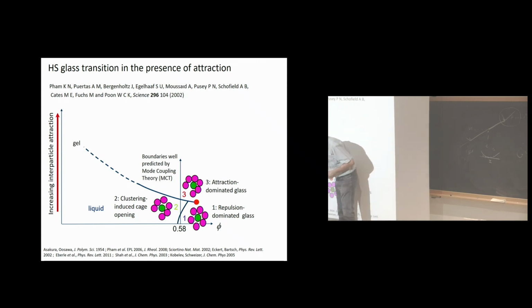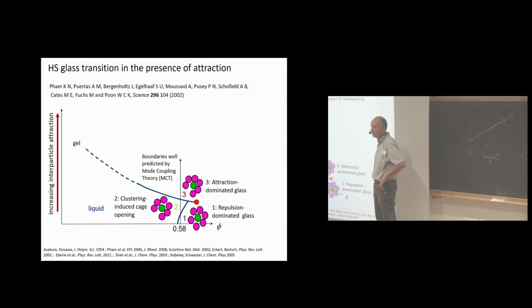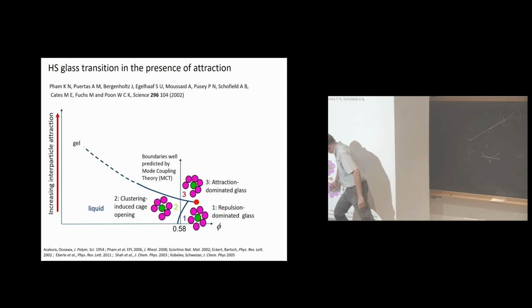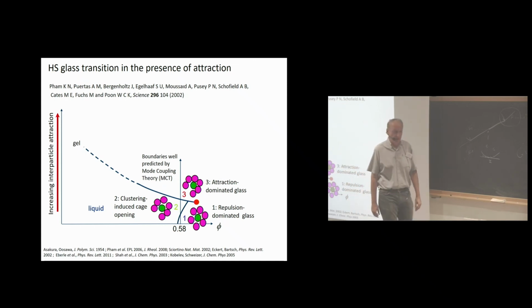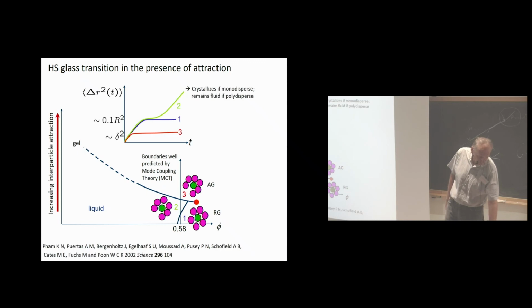And so here is the way they bond, but by bonding, okay, means that somehow a particle will bond to another one, but it will create a little bit more free room. Okay? In this respect, there is some opening of the cage, right? And so you turn into a small liquid pocket. To have this, you need to have a narrow range of polydispersity, which we can discuss only if you're interested. And then on increasing, basically, the osmotic pressure, eventually you have what we call attractive glass, right? So that was the origin of two different glasses, repulsive glass and attractive glass in the system. And of course, the properties are uniquely different.